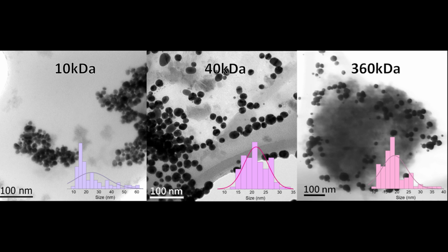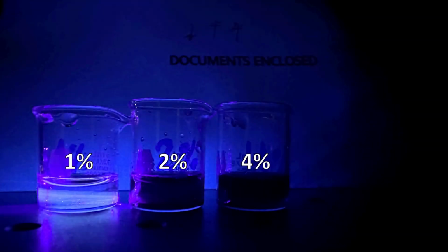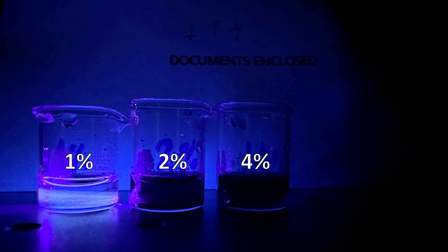These nanoparticles presented quasi-spherical morphologies and sizes as low as 18 nanometers for high molecular weights and a wider size distribution for the lowest one. The colloids prepared with 40K Dalton's PVP presented an interesting emission phenomenon due to luminescent gold clusters in the solution.